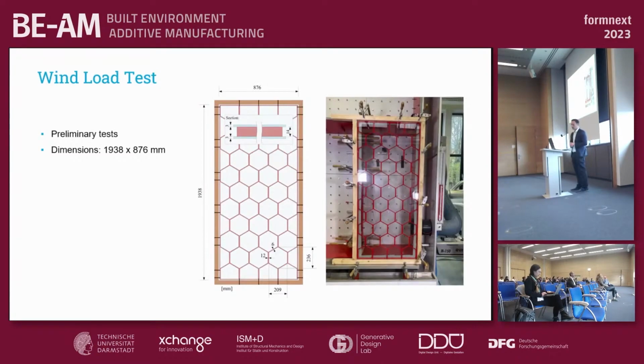You can see here already on the right-hand side the test specimen, which is built into the facade test wall. On the left picture, that's the technical drawing. That was only a preliminary test at first. Dimensions are roughly 2 meters by 1 meter in size. And you can see the honeycomb structure, which is 14 millimeter thick. It was a PETG based polymer with 20% glass fiber. And on the top, on each side, we glued a 3 millimeter thick glass sheet.